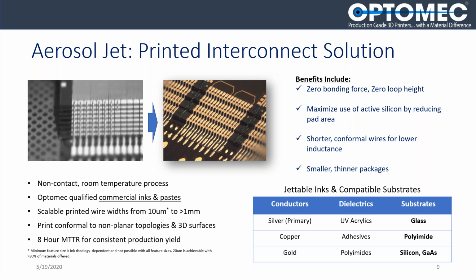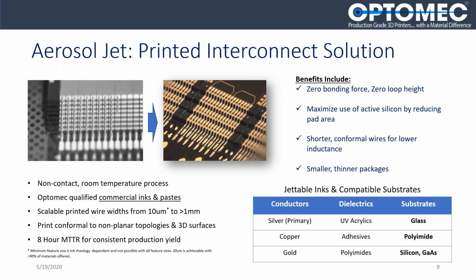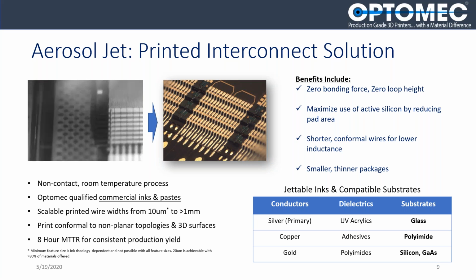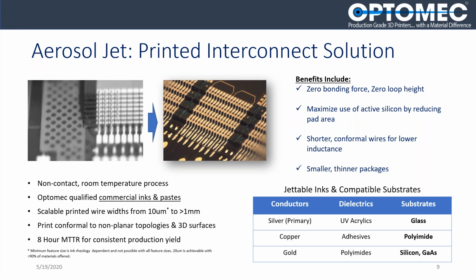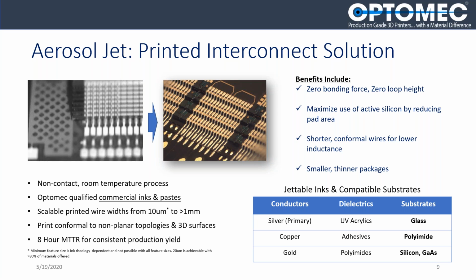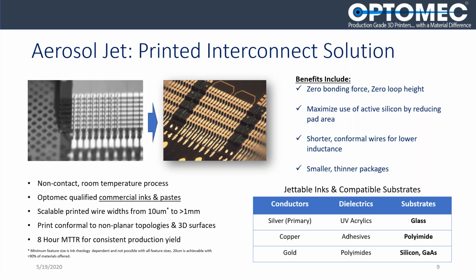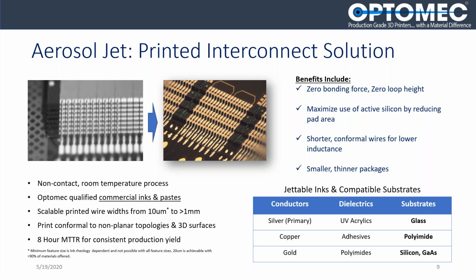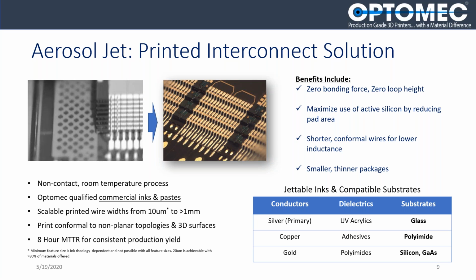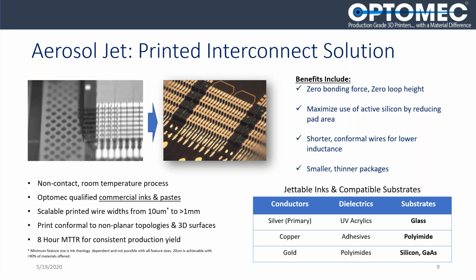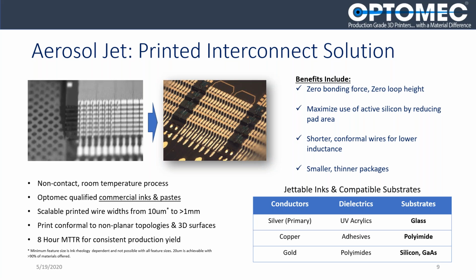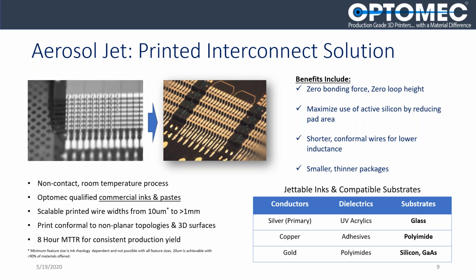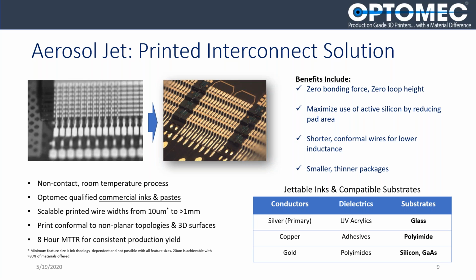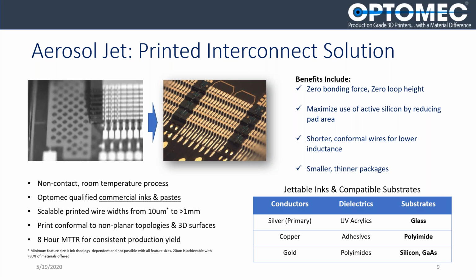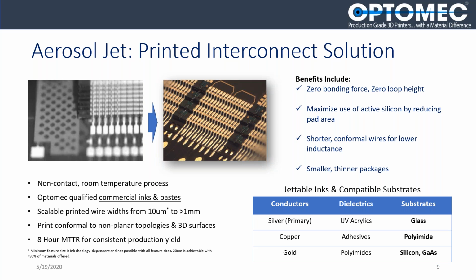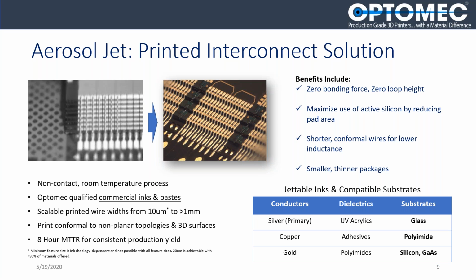And what you're looking at there is a 280 micron tall stack of thinned backgrind memory die that are stacked in a stair-step configuration, and we're printing a 3 to 5 micron tall, 35 micron wide wire up that 280 micron staircase. And this video is in real time. We're doing it about once every 800 milliseconds or so. And this is really empowering because this is all happening non-contact at room temperature. We're imparting 0 bond force to the component, and these 8 interconnects are replacing what would be normally taken up by a stitch bonding operation.